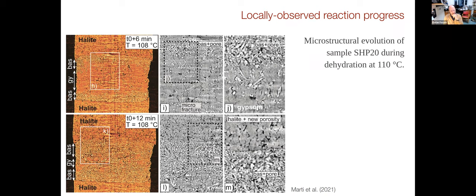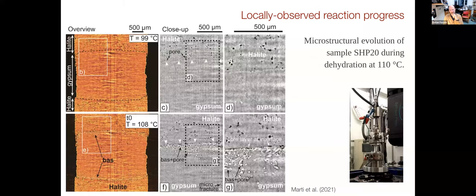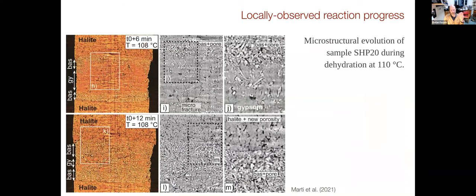And interestingly, if we look here, 12 minutes, then in comparison to earlier, and I'm going to show you that again on the next slide, the halite now also looks different. Maybe let's go back just to see. This is what we started with, and this is what it looked like 12 minutes later. Clearly, something has happened here, and also this layer at the interface is gone.